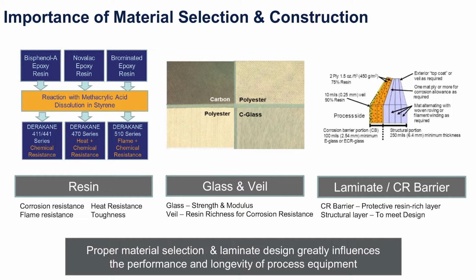For other lower temperature caustic type applications, you'll typically see a polyester veil. Typically Nexus is what you're seeing out there. And that polyester veil is very good because it's resistant to caustic attacks. It also performs well in hydrofluoric acid type applications, all that kind of stuff. All that information is in our corrosion guide if you're interested in that. But by and large, the big workhorse of the industry has been C glass veil over the decades.